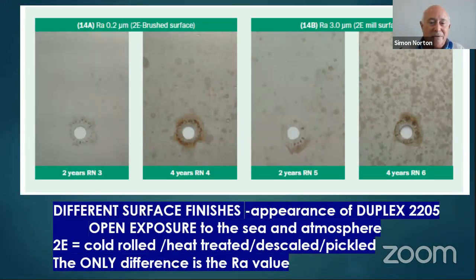On the left-hand side, and this is for duplex stainless steel 2205, you can see the impact. The left-hand two pieces show a 0.2 micron surface. The two on the right are 3 micron surfaces.